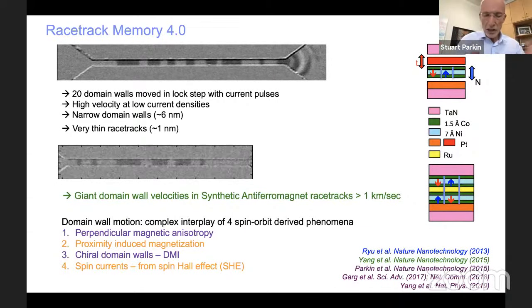So in summary, what's interesting is that this is a truly chiral spintronic phenomenon, where we have chiral domain walls set by the Dzyaloshinskii-Moriya exchange across an interface with a heavy material with strong spin-orbit coupling, and we use spin currents from the spin Hall effect, which themselves are chiral. So these are very interesting interplays of chiral spintronic phenomena.